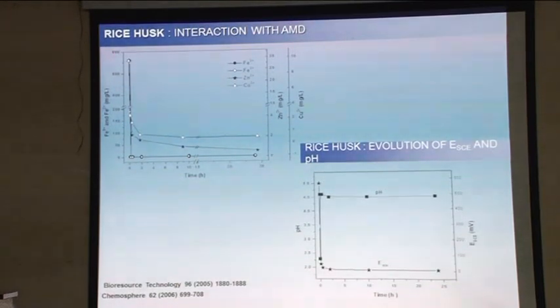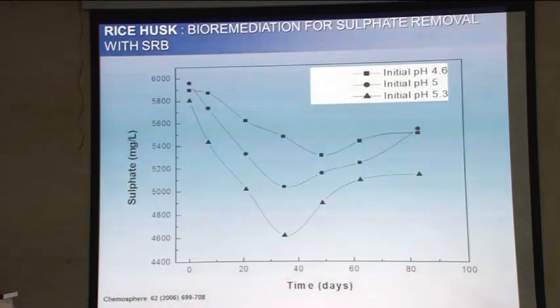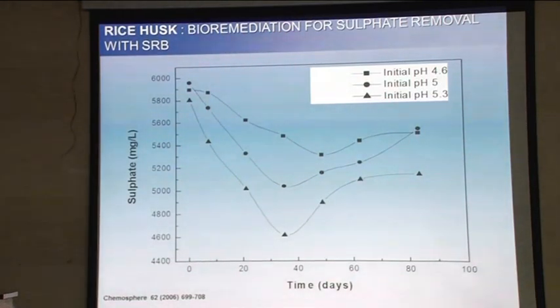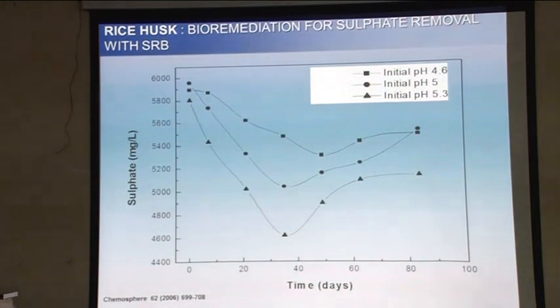So then the next step was to actually look at the sulfate reduction. So here again we see different pH values. Of course, this is a neutrophilic organism, so if the pH is closer to neutral, your chances of sulfate reduction are better. But still we wanted to know whether we can adapt this organism to low pH values, and you can see that the sulfate reduction actually takes a long time, but you can see that it is a function of pH.